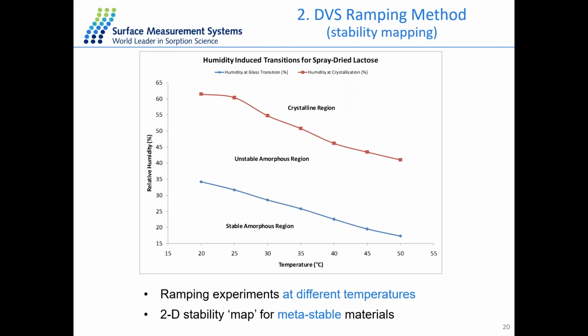And we can also perform the same ramping experiment at different temperatures. And at each temperature, we can get 2 points, glass transition point and crystallization point. Then we can plot this stability mapping of the material at a series of different temperatures. So if we have a combination of the condition we want to store this sample, for example, a combination of the temperature and humidity, we can easily predict the sample is at a stable amorphous state or an unstable state or the crystalline state of the material. So this stability mapping is quite important for the storage or the application of the pharmaceutical ingredients.